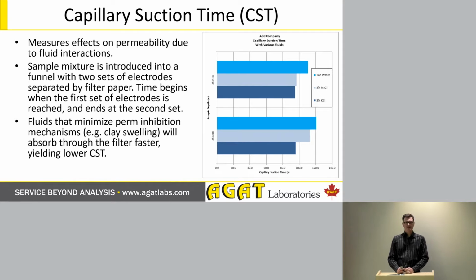Capillary suction time is somewhat similar, and what it's trying to do is show us how fast the sample will precipitate, or soak through a filter paper in different mixes of fluids. Similar idea, what we're looking at is how badly will the sample be inhibited from flowing through that filter based on the different fluids used and the interaction with the sample material itself. So the fluids that minimize the perm inhibition the most will absorb through the filter faster, so we get a lower capillary suction time. So that means that the faster times at the top there are the more effective